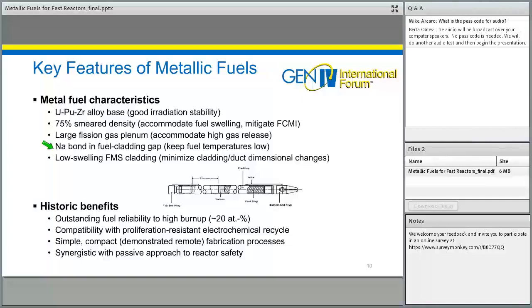So you need a large fission gas plenum to accommodate the high gas release. That's not really any different than MOX fuels in fast reactors. And then we've evolved to marrying this fuel technology up with low swelling ferritic martensitic cladding and ducts, which allow it to go to quite high burnup. Here's a little sketch of what I've described, a metallic fuel pin.